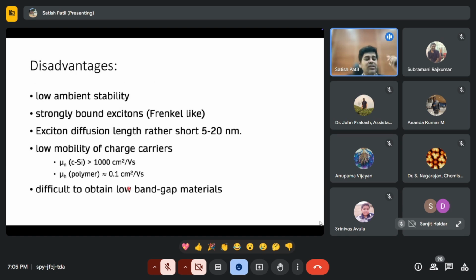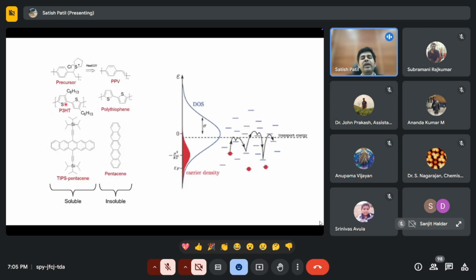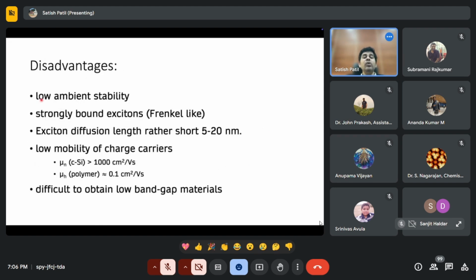What are the main challenges, and what are the research gaps now? One of the major problems with these materials is low ambient stability. These materials are based on carbon, hydrogen and heterocycles. If they are exposed to light for a prolonged period of time, these materials can undergo side reactions. For example, you have a lone pair on sulfur, which can get oxidized under very harsh conditions. So the stability of these materials is very poor.